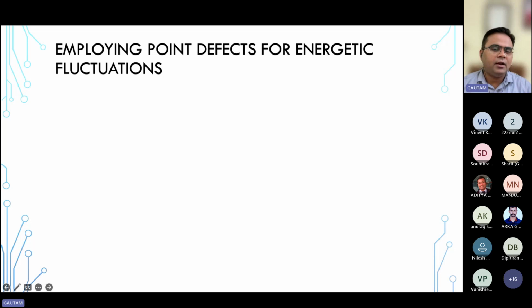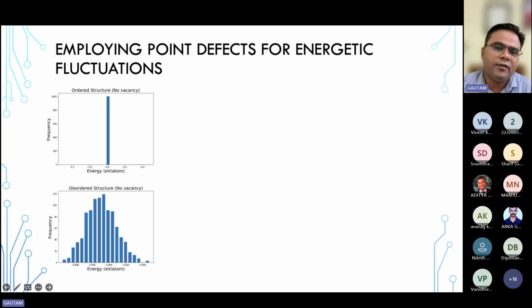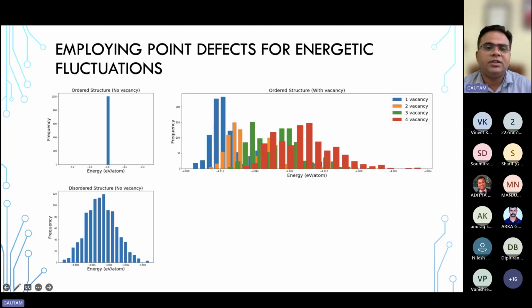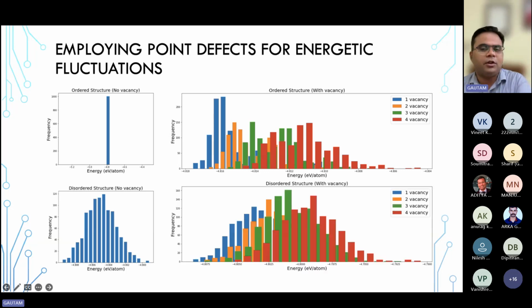But if you have binary alloys, it is difficult to create such energy fluctuations. Say you have an ordered structure with no vacancy, you just have one energy, right? But if you have a disordered structure, you have a range of energies. If I introduce the vacancy in this system, I generate the fluctuations in energy, and these fluctuations can have the entropy associated with them. Similarly, introduction of a vacancy leads to fluctuations in the disordered structure also.